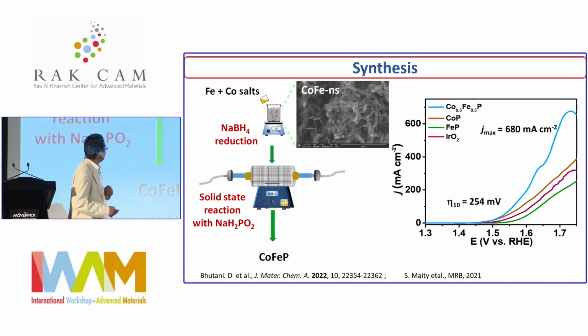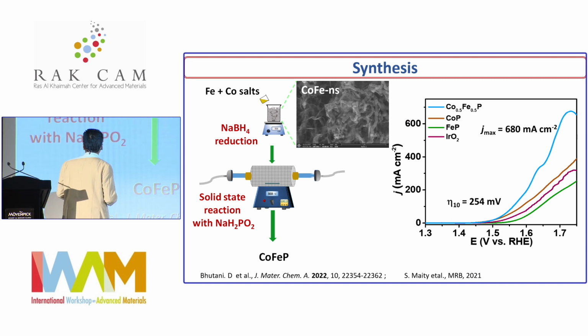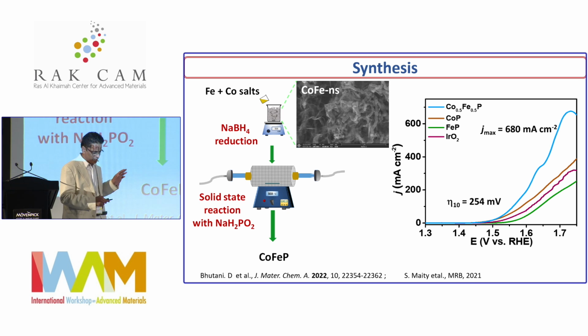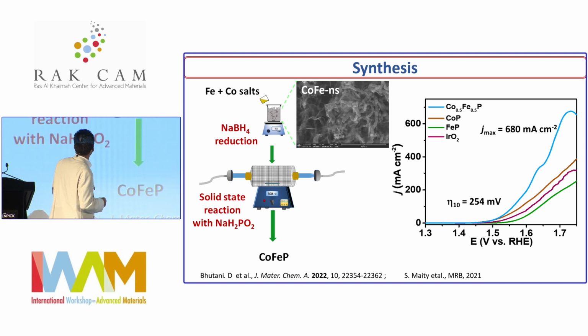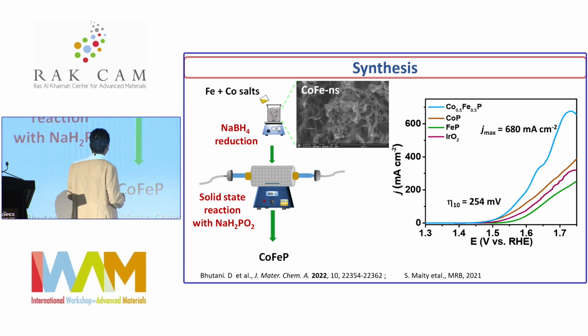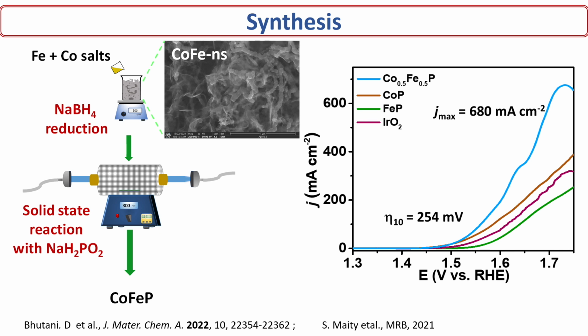So here the same method we have used: we have taken the cobalt and iron salt, with a simple sodium borohydride reduction, optimizing the kinetics by concentration and temperature. Then the obtained hydroxides of iron and cobalt are phosphorized to get cobalt iron phosphide. Here we have taken both the salts in the same solution, followed by the reduction. You can look at our LSV results compared to iron phosphide and cobalt phosphide, and this is the iridium oxide standard control. And this is 1:1 cobalt to iron that we have taken.